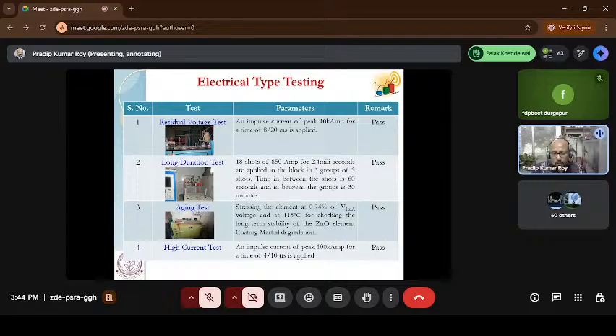The high current testing tells how useful the coating is, and how successful the coating is after maturing that glass coating. For that we need a 4 by 10 microsecond impulse at 100 kiloampere current, and that tells the strength of the glass coating you put around the block. Then this ageing test is required. The ageing test normally tells whether any kind of leakage is happening through the blocks or not. As I said, it's an outdoor application, so we also check whether any humidity effect is affecting their performance.